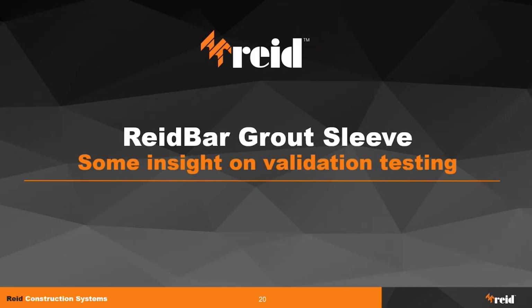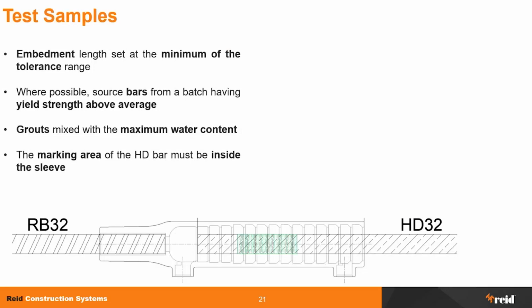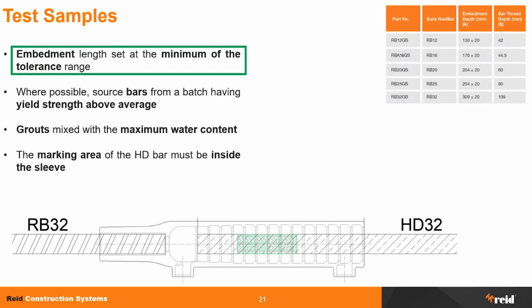Now I would like to give you some insight on the validation testing and what we considered together with Home Solutions and BRANZ, of course, to validate the system and how to test for these changes that we have introduced. If we look at, for example, the 32 mil grout sleeve, we have introduced this new tolerance range for the embedment depth. Now the embedment depth is 300 plus or minus 20. Therefore, for the test samples, we ensured that the embedment depth was set to 280.